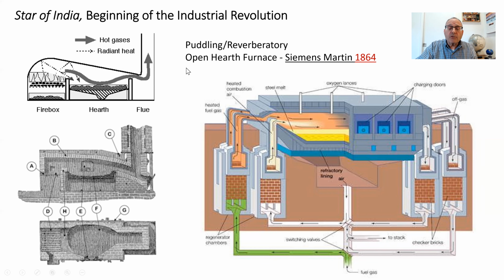And the open hearth process was developed near the end of this, and it was improved pretty significantly by Siemens and Martin, where they designed these really huge open hearth furnaces where they had molten steel or molten iron in here, and they'd roll the hot air and recycle it around, mix it with fuel, and come back through and reduce the carbon level down to a low carbon forgeable steel. But now notice that this was in 1864. That was the most efficient and best process that had been developed at that time. And this was about a year after the Star of India was launched.